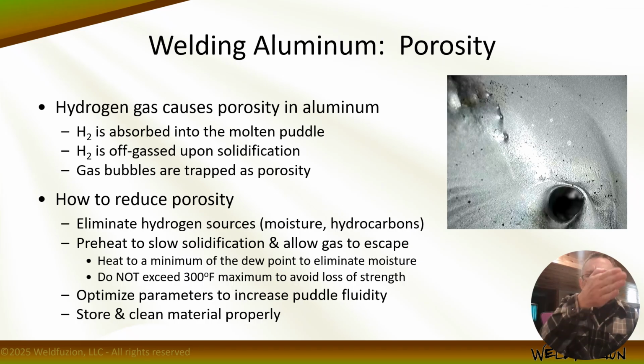You want to store it on its edge, right? That way the edge is the only thing exposed to the surface if we're stacking multiple sheets together. All right, that's right. Stand it up on edge. Allow your aluminum to normalize to temperature. Don't store it outside ever, for one. It's not good practice. And don't put it in the shop 10 minutes before you plan to weld unless you don't mind a little bit of porosity in your welds. It's a good idea to let aluminum normalize to temp over 24 hours before processing.